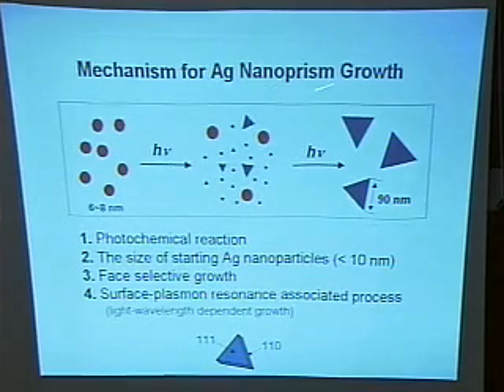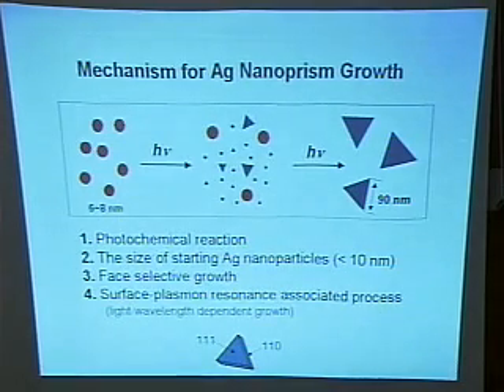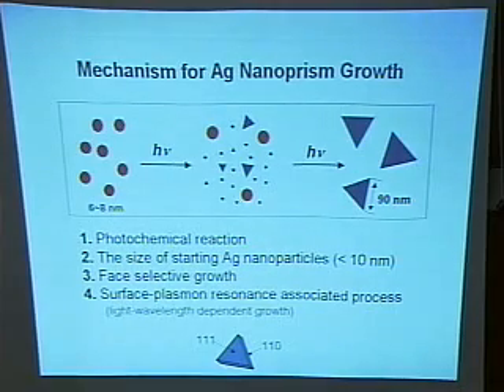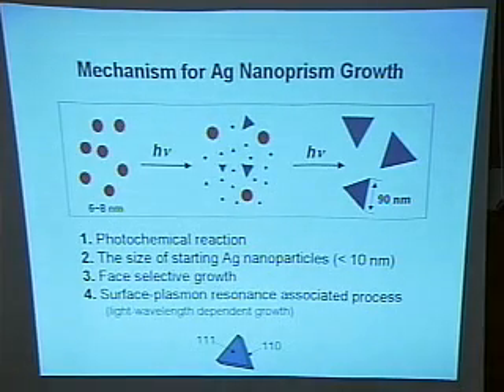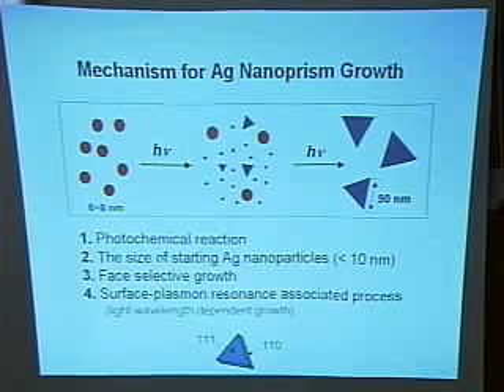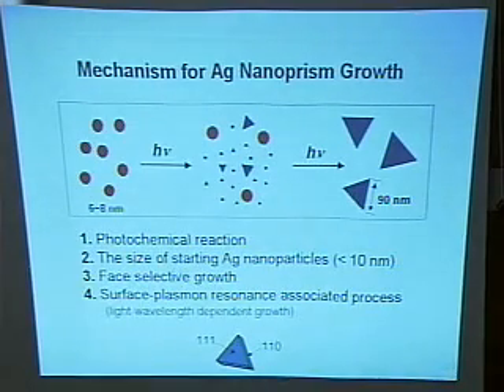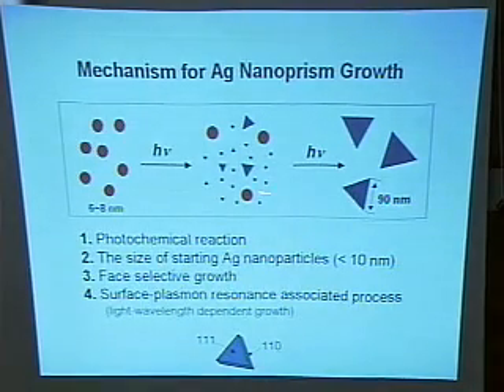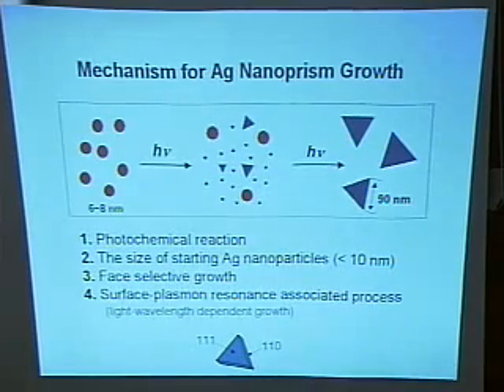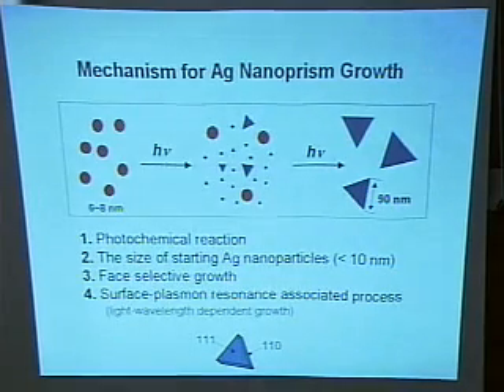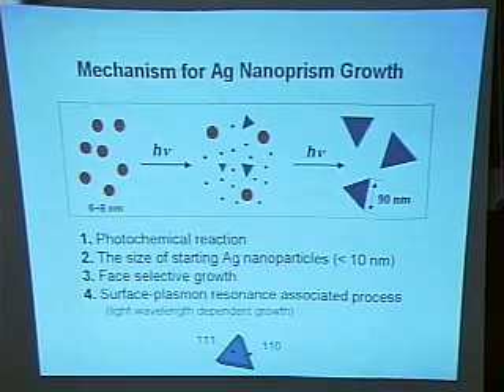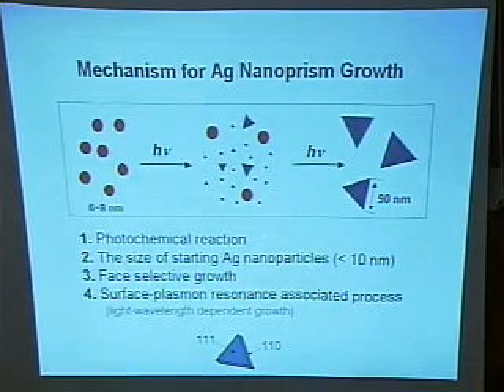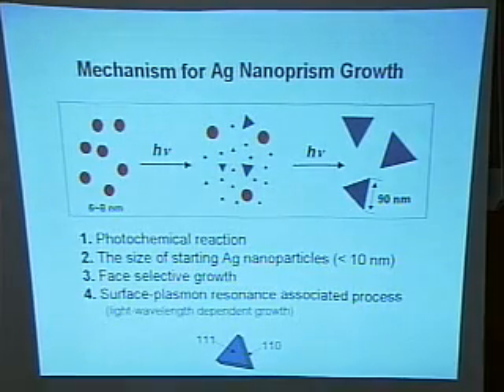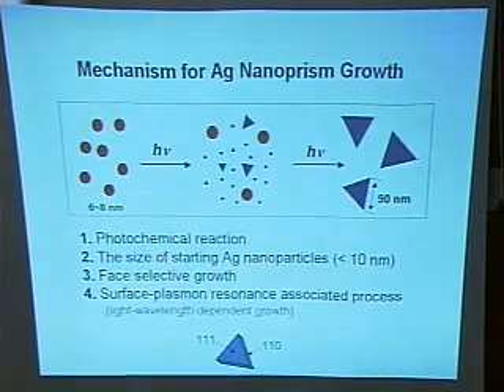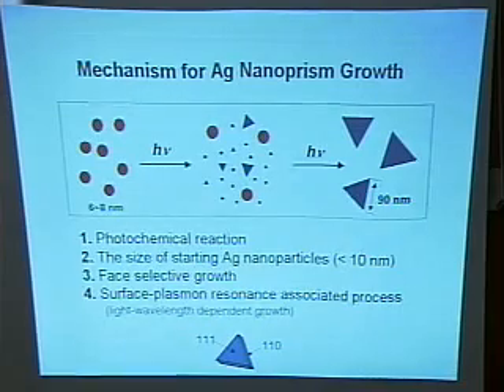And this process is a photochemical reaction. Turn off the light, nothing happens. And the size of the starting silver nanoparticle is important. If you use 20 nanometer particles, it doesn't work. You have to use smaller particles. And this is phase selective growth. The top and bottom are 1-1-1 phases. So this gave us a triangular shape.